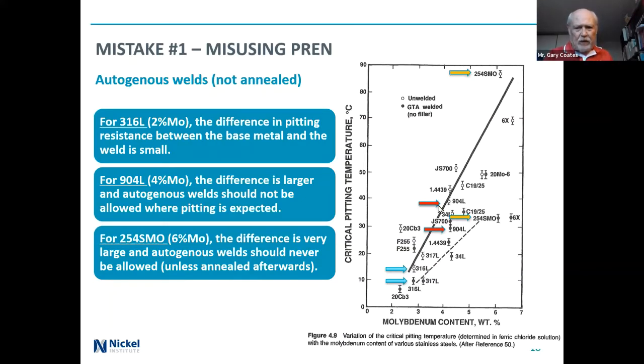When we get to 904L, which is the red arrows here, the difference becomes a little bit larger, and certainly in any environment where 904L is used, has chlorides and where pitting is expected, you really should not use autogenous welding. And for the 6% molybdenum alloys, 254 SMO, Al6XN, for example, there is a huge difference, as these orange arrows show, and you should never, ever allow autogenous welds unless they are annealed afterwards. Annealing will restore the uniform molybdenum content in the material, so molybdenum that has segregated will diffuse back, and you'll regain the corrosion resistance, the pitting resistance.